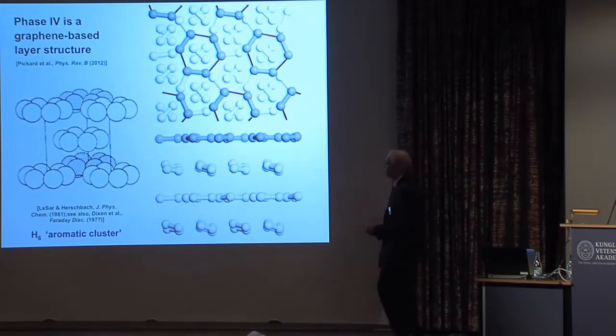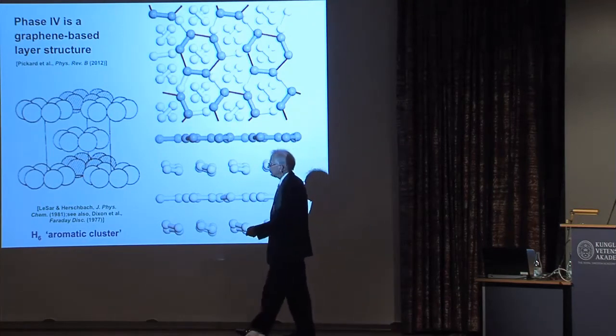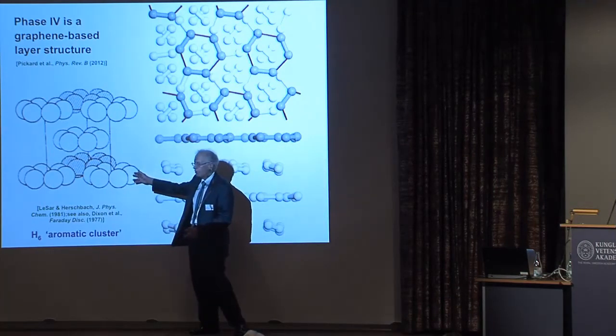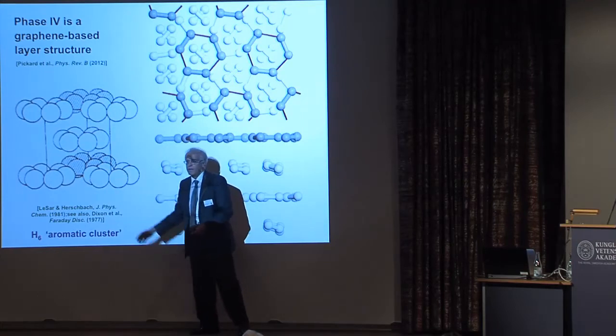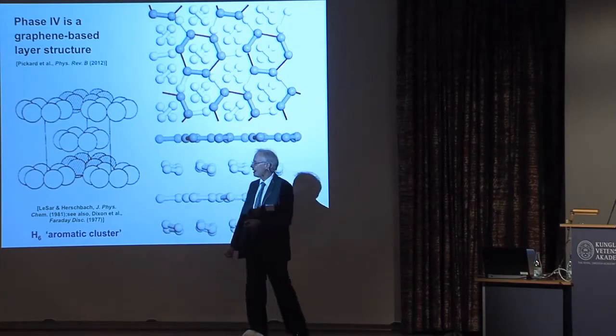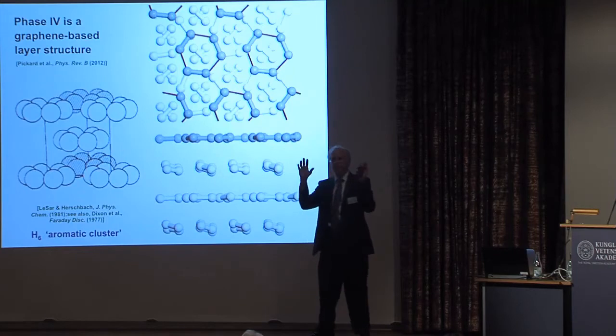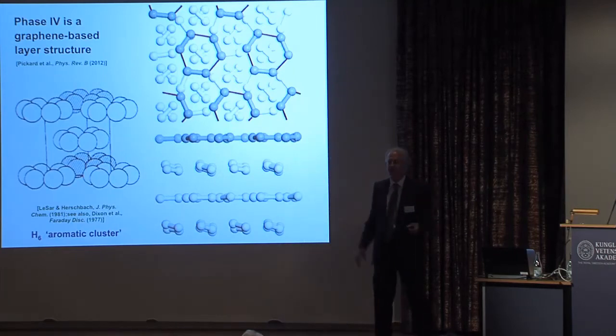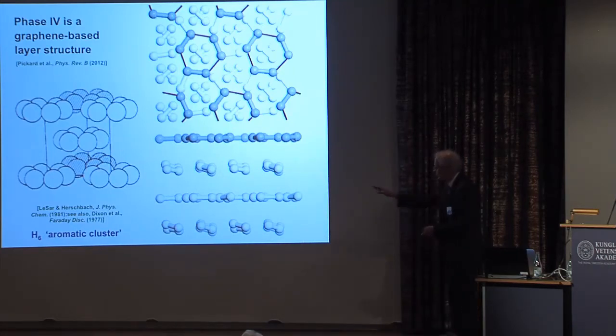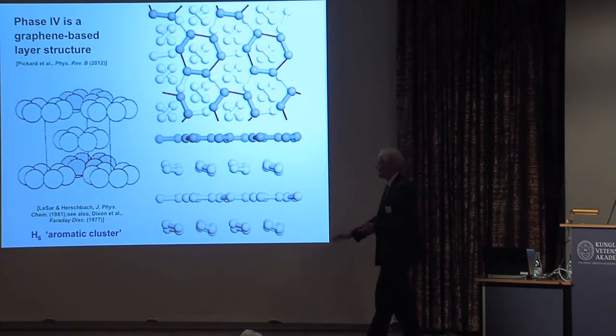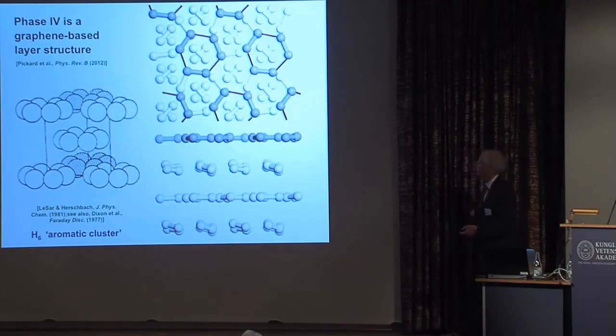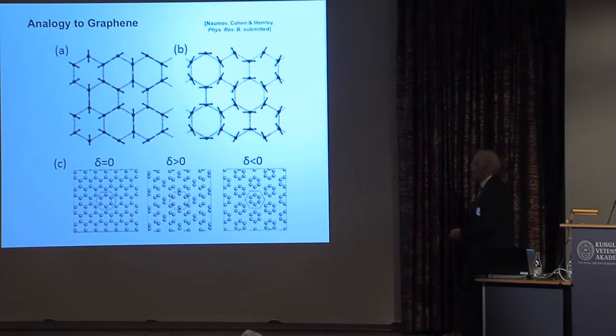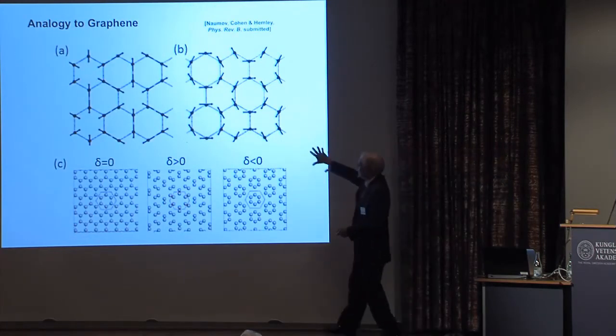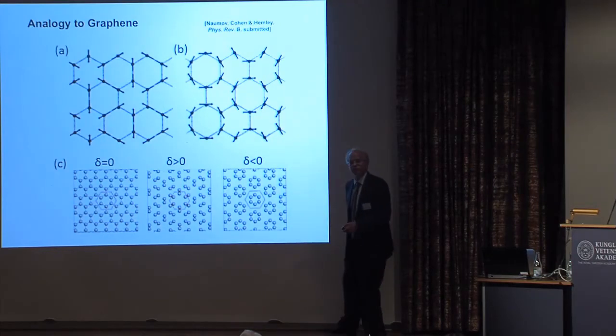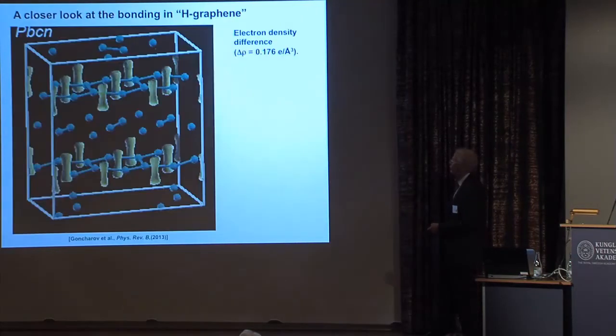However, chemists knew about this a long time ago. Dudley Herschbach, in fact, predicted at high pressure that there is stability of six-membered rings of hydrogen at high density in a type of aromatic cluster, rather like what you have in benzene. He published this in a paper in the Journal of Physical Chemistry, where it was buried for many, many years, and people were unaware of those results. So this is an example of what we see here in the layers, different kinds of distortions of the hydrogen molecules in this graphene ring.